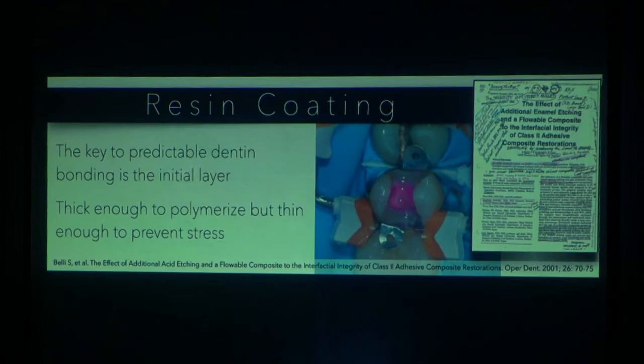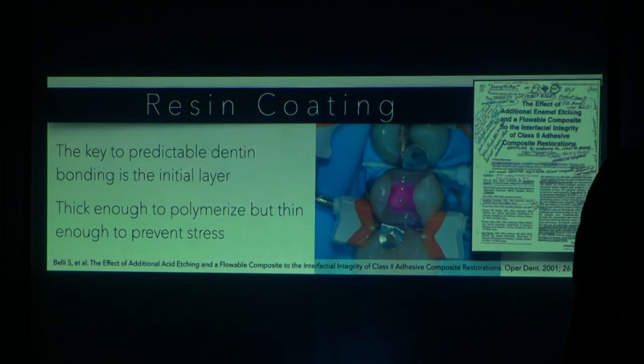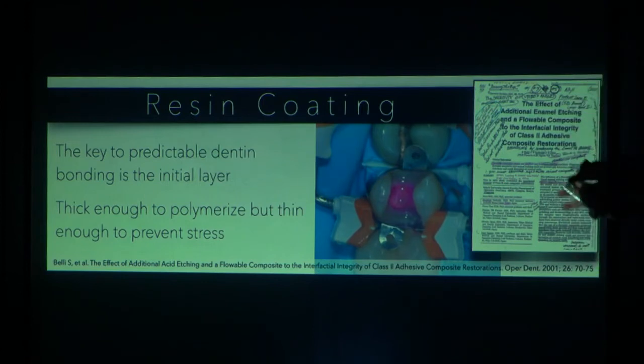This is important science. I mean, everybody in this room, they're still here, right? Hey, you don't have to give this lecture tomorrow. All you have to remember is don't get thicker than 1.5 millimeters in the first 5 minutes after you polymerize your adhesive layer. That's the secret. All right. So the key to predictable dentin bonding is the initial layer thick enough to polymerize but thin enough to prevent stress. And that thinness number is that 0.5 microns that Deesha showed you with her perio probe. Davey taught you about the resin coating protocol.